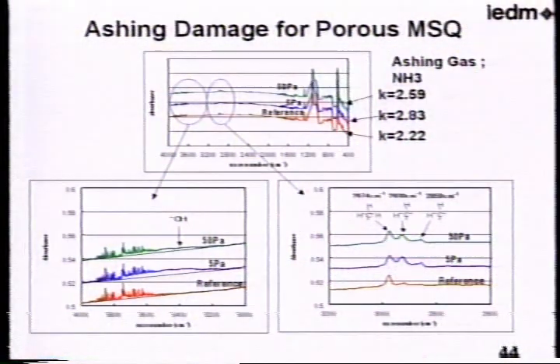And etching damage is also very big concern for low-K integration. This figure shows porous MSQ, FTIR spectra after plasma treatment. The sample is porous MSQ. Ashing gas is ammonia. In that case, we change the pressure of ammonia. As you can see in this figure, after etching, the K value is increased much, like 2.2 or 2.5. Simultaneously, we can see a water desorption in the film, and the chemical bond CH3 was broken. This is some damage of etching.